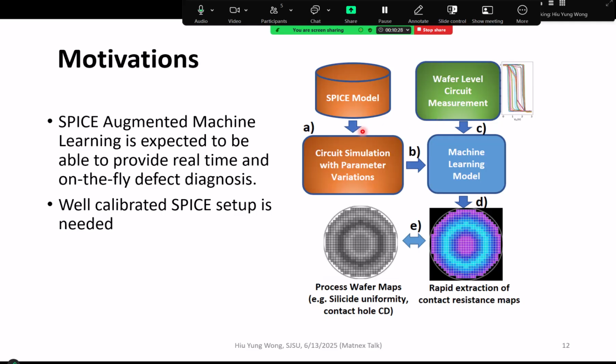We can, because SPICE is very fast, we can vary the parameters. For example, how about we add a contact resistance to a MOSFET and put it in an SRAM or inverter circuit? We build a machine learning model, right? And then during the measurement, you just probe the wafer. You can use the machine learning model to invert or to deduce what the contact resistance of that inverter is. So in the past, you needed to do failure analysis. Now with some preliminary metrology, you can extract the contact resistance of each transistor in a complicated circuit.